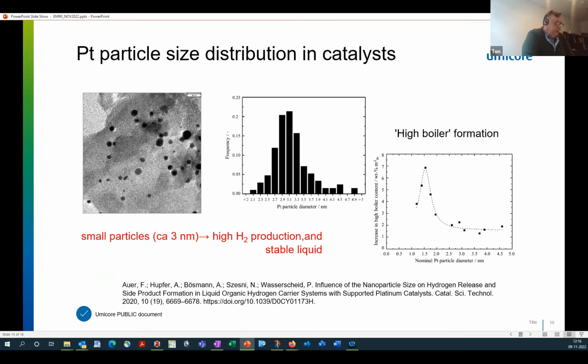Then another point is that to have enough catalyst activity, we want to have small particles. And we are actually aiming for particles that are about 2, 3, 4 nanometers in size. There is another point to be considered, and that is that there may be unwanted side reactions.